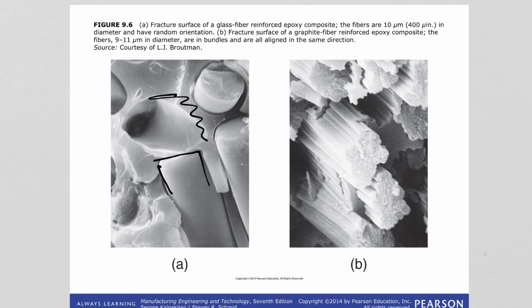So we also see the fracture surface of a graphite fiber reinforced epoxy composite. In this case, we are seeing the fibers are in bundles, not individually dispersed. They are bundles, and all of these bundles are aligned in the same direction in the structure, and they are again between 9 to 11 micrometer in diameter.